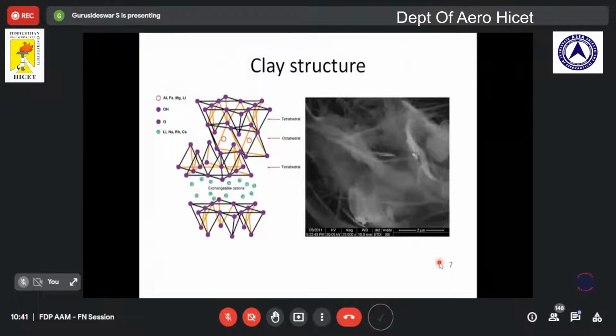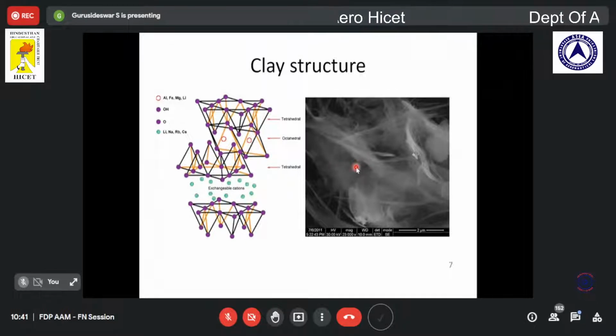Clay structure. Here I have given the structure of a nanoclay, and the right-hand side shows a typical scanning electron micrograph of a raw clay. This has been taken at around 23,000x magnification. You can see it's like a layer. It has a nano-size thickness and a micron-size length. But this clay is in raw form. It is in an agglomerated state. This clay is not dispersed in a matrix. We simply took a pinch of clay and got this micrograph. This was taken using scanning electron microscopy, we say SEM. You can see this is the micrograph of nanoclay.